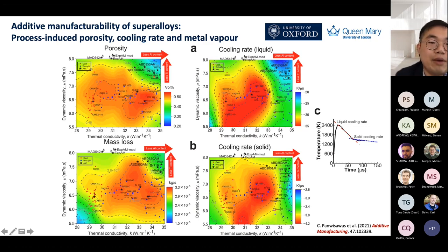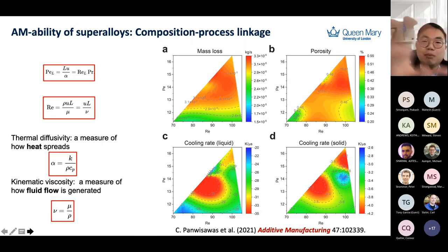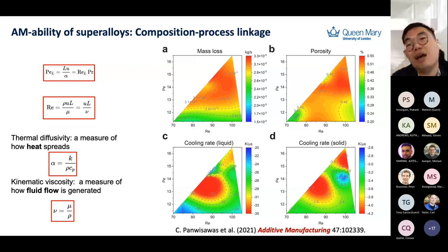And this is because if we understand this interaction and summarize the map for superalloys here, you will see that there are some hotspots from the thermal fluid point of view where you can get a processing window, avoiding a lot of mass loss or getting quite an optimum cooling rate. And I have to note that this is at a condition investigated. So we need to use this information to optimize further for a particular material, process, and machine as well for additive manufacturing.